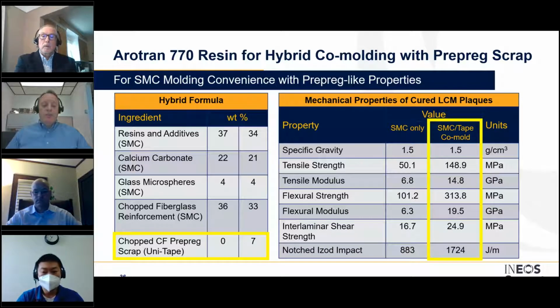In making the panels whose properties are shown in the right-hand columns, however, we laid a small amount of continuous fiber unidirectional tape left over from the prepreg work that I just discussed underneath the SMC, orienting it in just one direction. So when the co-molded SMC and the prepreg tape were evaluated in the direction of the continuous carbon fiber, we observed really remarkable enhancements to strength and modulus, roughly doubling or tripling those values, as you can see, even though the continuous fiber prepreg amounted to really only a very small volume fraction of the finished part. The impact performance also approximately doubled, as you can see.